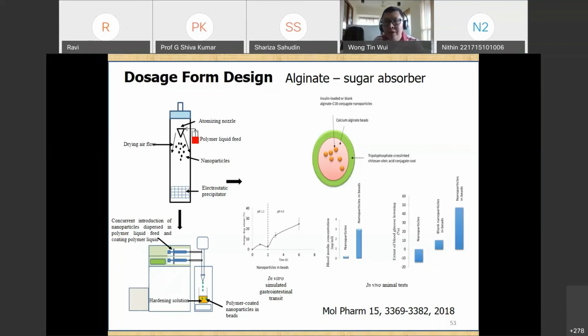So the alginate-C18 conjugate nanoparticles are later loaded into calcium alginate beads, which are larger in size, about 1 to 2 millimeters. And you note that the bead material is alginate. That's because the bead material is available in a larger quantum. So using a larger amount of alginate, it can also confer a sugar-absorbing property that will help us to reduce the rise in blood glucose in the systemic circulation.